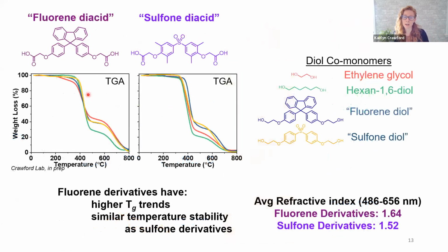And so an important thing to characterize here, or 2 additional important things to characterize, is, 1, do they still have high temperature stability? And so we measured the thermogravimetric analysis, or the TGA, that shows us indeed most of these have high temperature stability despite their chemical modification. And so for frame of reference, most organic polymers tend to degrade above 200 degrees Celsius. And so these polymers are robust up until about 400 degrees. And even though this red ethylene glycol derivative looks to be degrading a bit earlier, statistically, it's insignificant when we ran multiple trials.